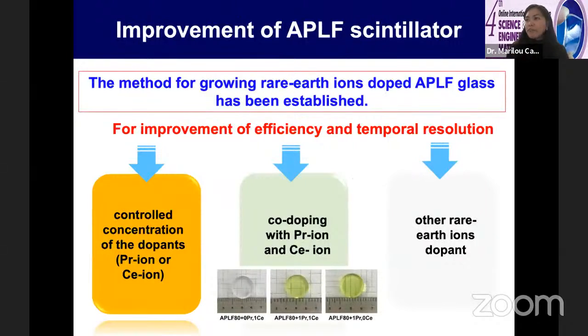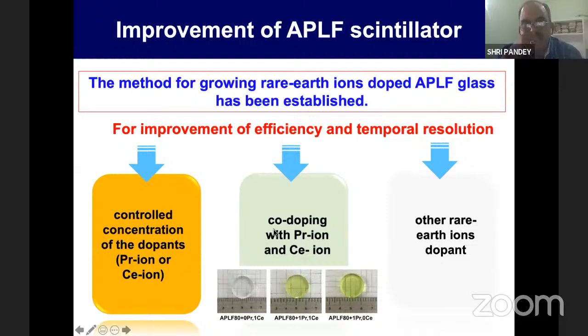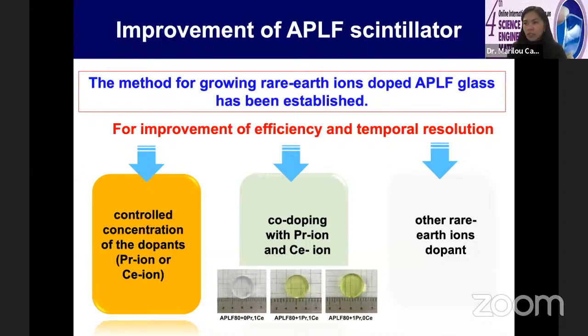So now that we have successfully grown rare earth ions doped in APLF glass, we now have to improve the performance, especially the light yield, the photon yield, and the efficiency of the scintillator. So we are looking at 3 approaches to do this. We can either control the concentration of the dopant ions, or we can co-dope our APLF matrix with both praseodymium and cerium. And we can also look at other rare earth ions such as erbium or neodymium, as I've shown earlier in the slide. But in this talk, I will discuss the results on co-doping with praseodymium and cerium.